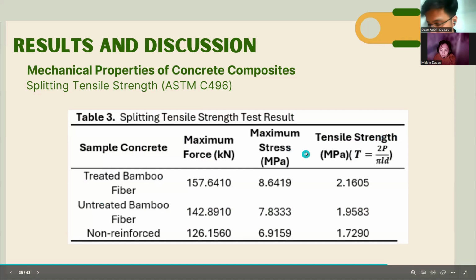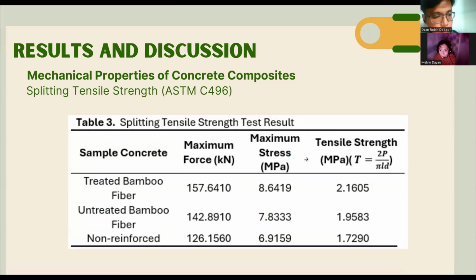And for the mechanical properties of the concrete composite, the maximum load and sample dimensions were used to calculate the corresponding tensile, flexural, and compressive strength. For the splitting tensile strength test, the table presents the test results, including maximum force, maximum stress, and calculated tensile strength. Treated bamboo fiber reinforced concrete exhibited the highest performance with a maximum force of 157.6 kilonewton, a maximum stress of 8.64 megapascals, and a calculated tensile strength of 2.16 megapascals.